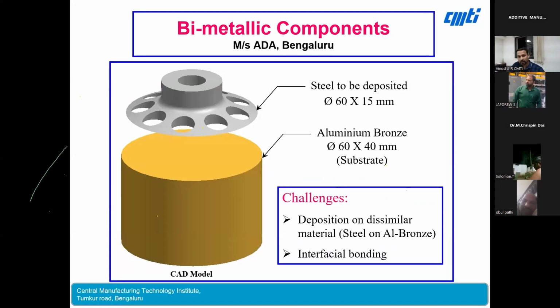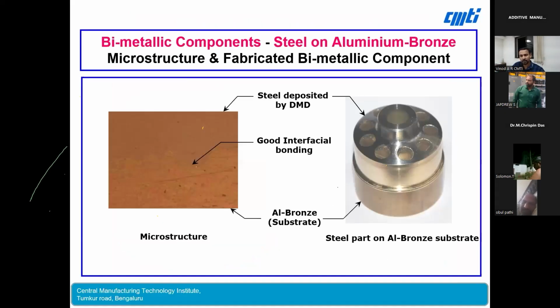Here we have to join the steel on top to the bronze on the bottom. These two different materials have different properties, different thermal expansion coefficient, different melting point, so different specific heat. Especially when you have two different materials having different properties, it's difficult to join. Generally we use friction stir welding-like processes for joining, but there you cannot ensure uniform bond throughout the surface. So that was a challenge which was faced, and we could successfully develop a technology wherein we can deposit this steel onto the bronze base, so that we are able to get good interfacial bonding between the two different materials. And finally you can see this is the bimetallic pump part, axial piston pump made for aerospace application.